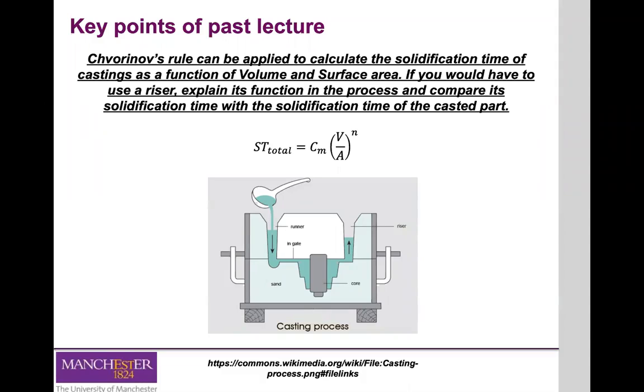It is important to know the specific volumetric shrinkage of each material so you can calculate the volume of your riser and ensure enough material is available to compensate for volumetric shrinkage. You need to know how to use Chvorinov's rule not just to calculate the solidification time of your parts, but also to calculate the solidification time within the riser, to ensure you always have material in a liquid state to fill in the gaps left by shrinkage during solidification.